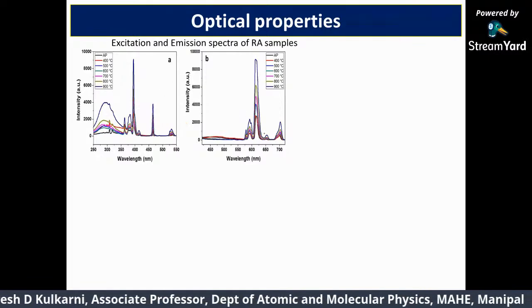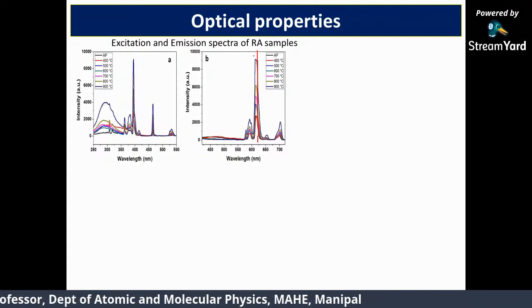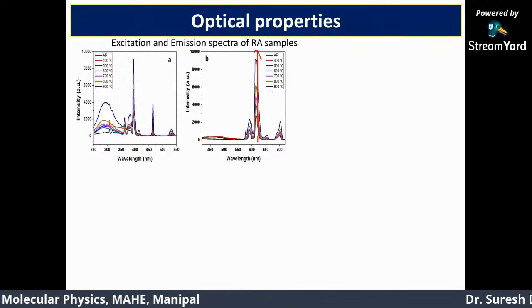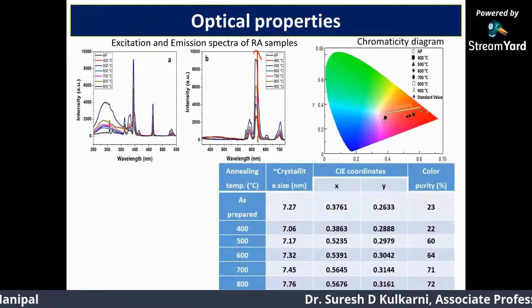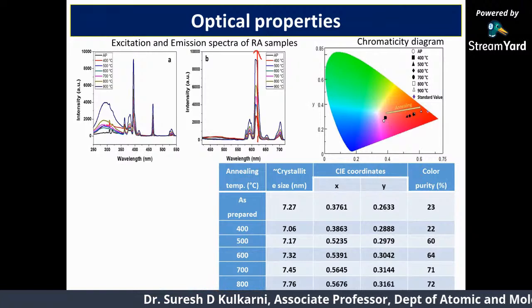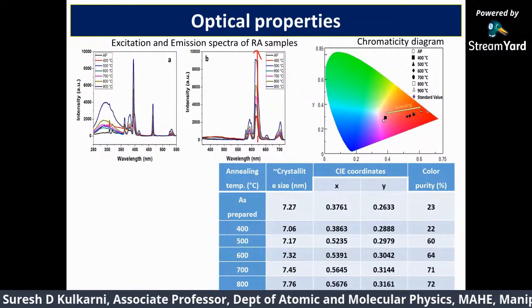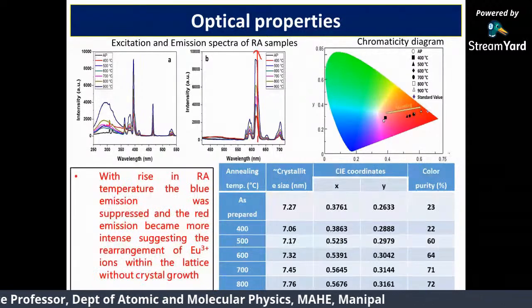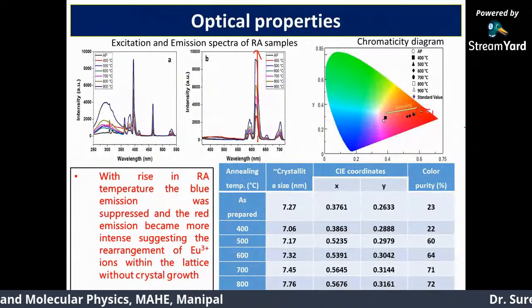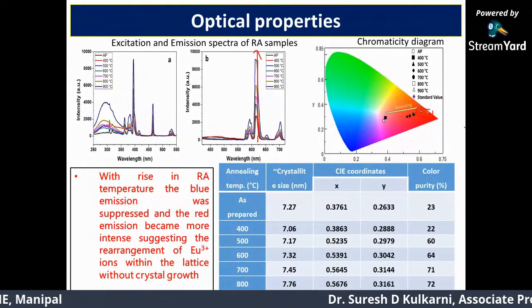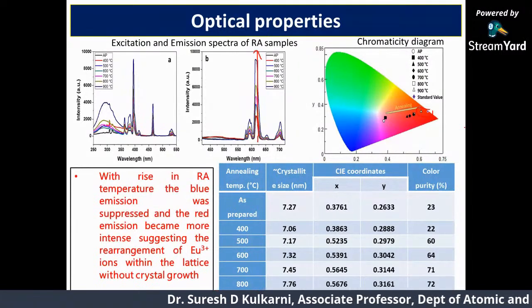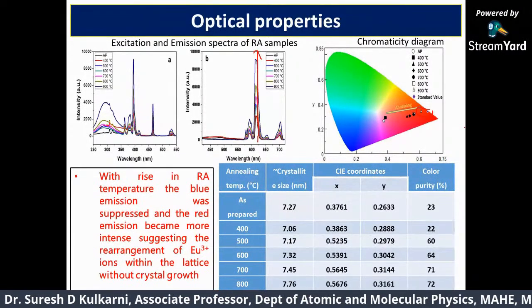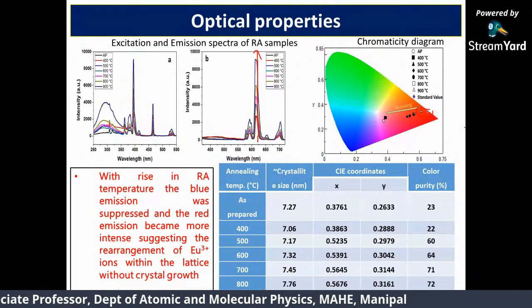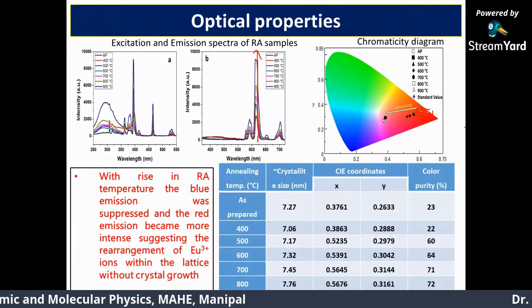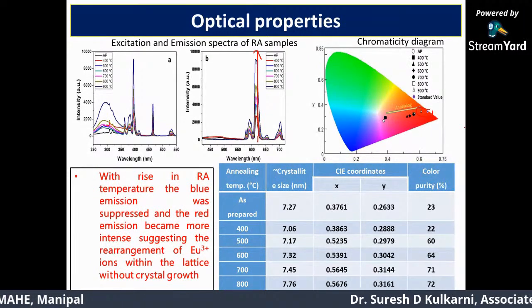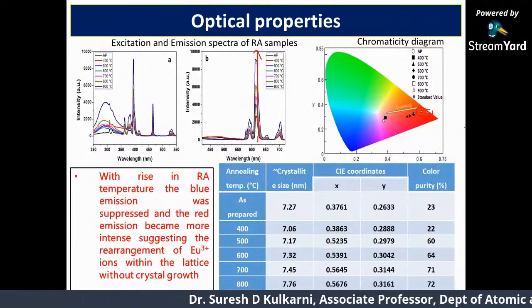You can see that the red color emission intensity is increasing with temperature here. Okay, and you can see that the material is showing a good score, 84% color purity. Compared to the television set standard, the standard is here, and our material is showing 84% color purity. All this takes 10 minutes using microwave synthesis and few minutes using rapid annealing, about 15 minutes. So altogether within 1 hour, I start from starting material. Within 1 hour, I get a technological material in hand. That is something remarkable by combining the two techniques.